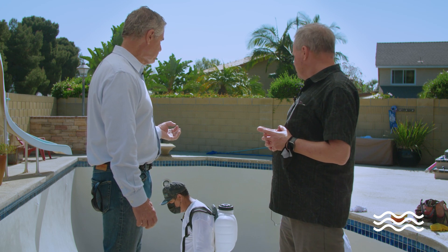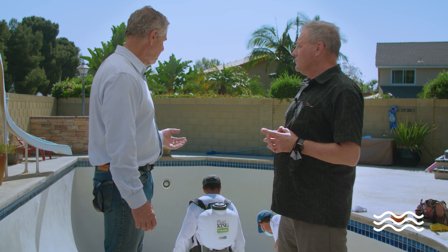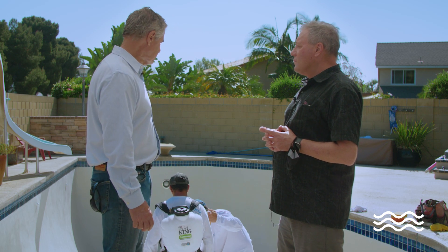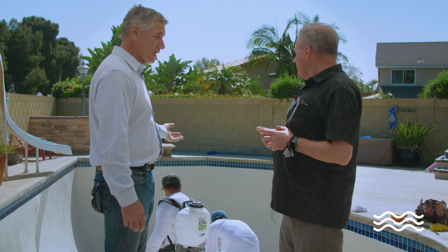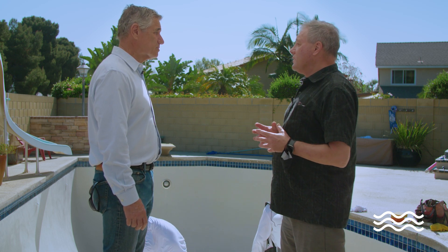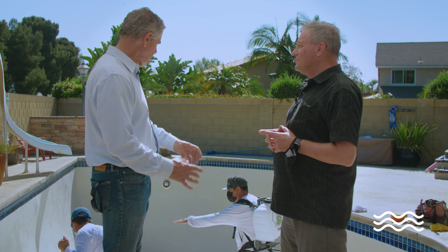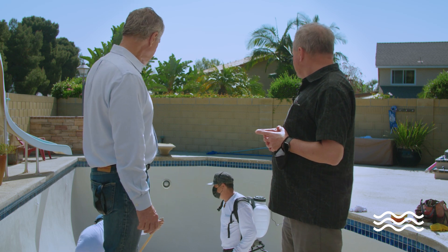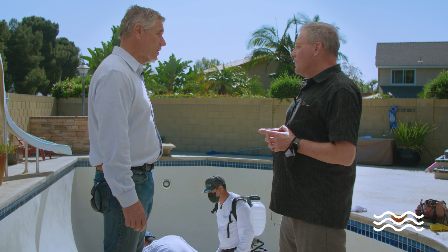Silicates are like glass — so arguably this is almost like an internal ceramic finish on there. We have jobs we've been doing for years now that are all successful. We have a job about six months ago — we did a pool very similar — this had thousands of nodules on it, and six months later, maybe one or two little tiny ones. So it basically took care of that problem, just like this pool. And we identified today that these nodules weren't related to delamination. The nodules themselves were just growing out of the wall, no hollows or anything like that. In the whole pool, we found one little hamburger-sized area that was hollow. Most all of these were just water pulling calcium out of the void structure throughout the pool.